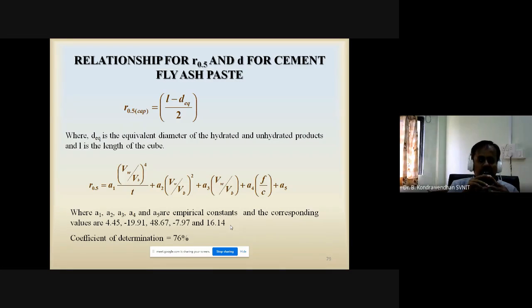So the equivalent diameter concept we used here, and we calculated the r 0.5 capillary entry radius as the length of the cube, that is, L minus d equivalent divided by 2. By using this, we calculated the equivalent diameter of the hydrated and unhydrated product, and L is the length of the cube. By using this, we calculated the capillary entry radius. Then again, beyond the curing age of capillary segmentation, the pores are gel, as I mentioned earlier. So again, we have to determine the gel entry radius.